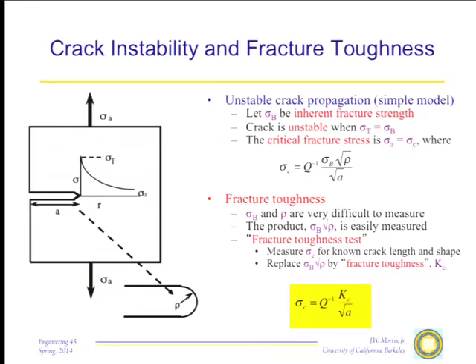Now, if I look at that and I say, well, I'd like to have some material property that lets me calculate this easily. My problem is that on the right-hand side of this equation, if I'm going to do sigma c and do this theoretically, I would have to know the breaking stress, which depends an awful lot on the microscopic mechanism of fracture, and I have to know the crack tip radius, which depends on what, if any, plastic deformation I get as the crack loads up. So these are things that not only are difficult to predict, they're very difficult to get hold of experimentally, individually.